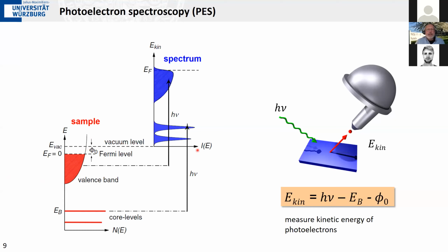And then as you excite these electrons with a given photon energy, you can excite them across the vacuum level. The distance between the vacuum level and the Fermi level, to which we refer our binding energies, is just the work function. And then you will see that the energy distribution of the photoelectrons will simply reflect the energy distribution of the electrons prior to the excitation.